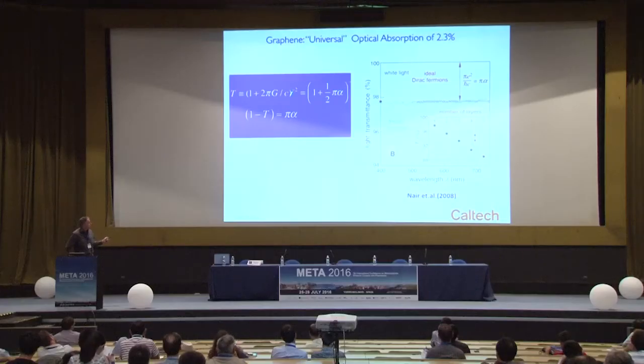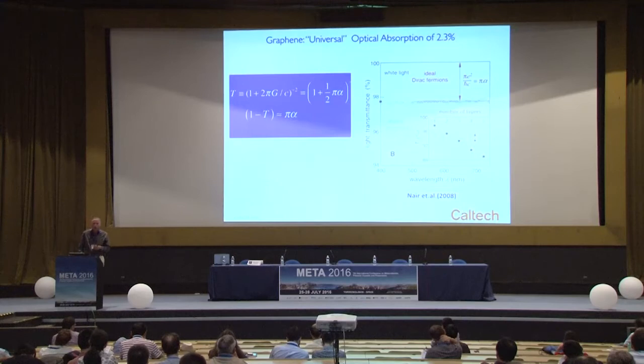And if we think about graphene as a metasurface material, it has some very interesting properties. We can make nanoscale resonators in extremely short wavelength. But graphene, as an extreme material, has very high optical absorption per unit thickness, but of course it's only one atomic layer thick. And its absorption, which you can obtain from fundamental considerations, essentially from the extreme two-dimensionality of the density of states, emerges as this simple expression for the absorption in terms of fundamental natural constants, pi times the fine structure constant. If you multiply pi times 1/137, you get an absorption of 2.3%.